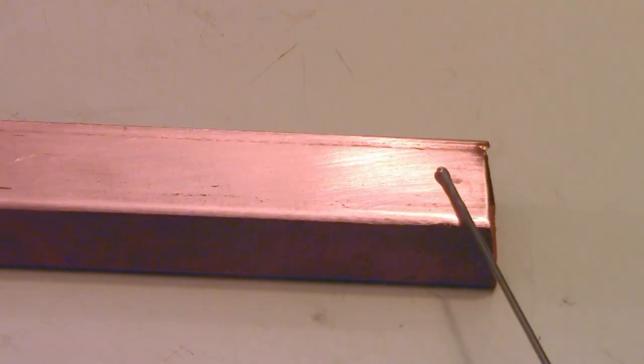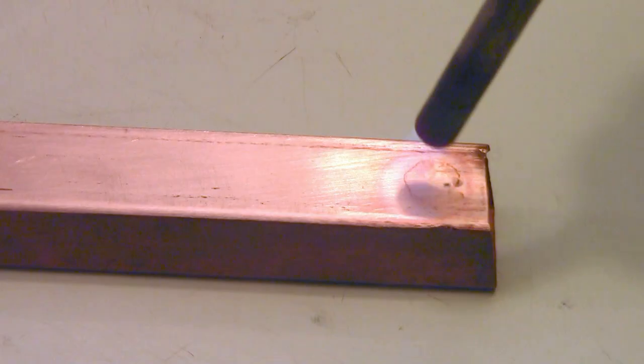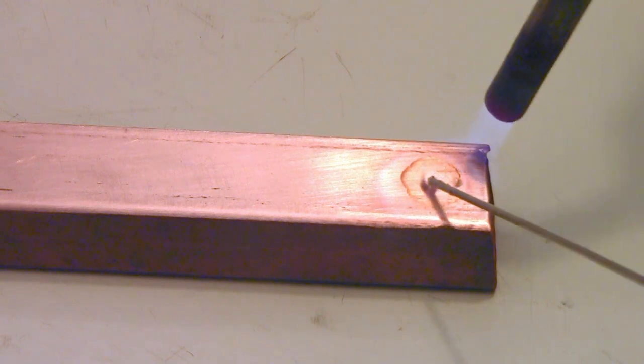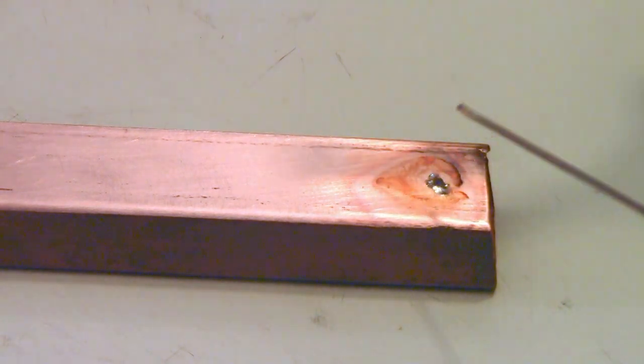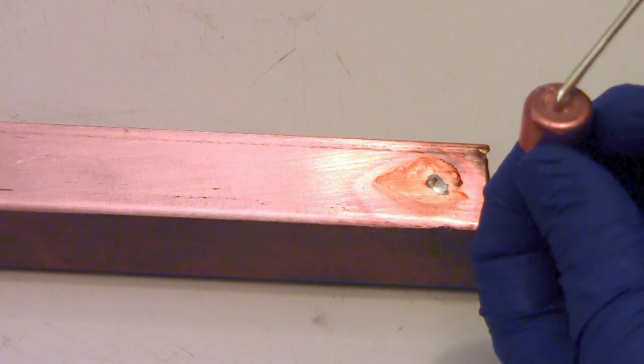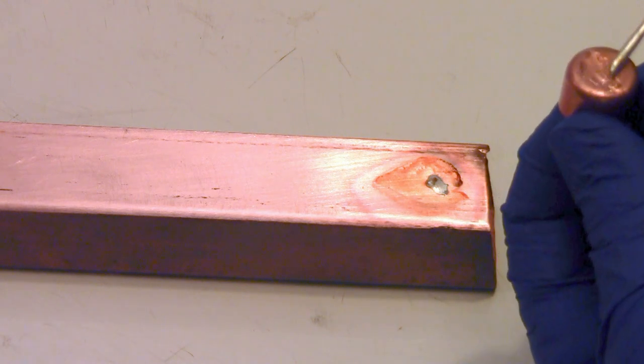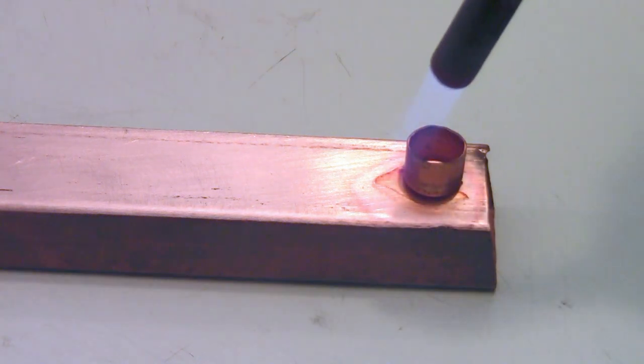Sometimes you want to hide the appearance of the solder. Here's an easy technique. Add the flux to one part, heat like always and add a small amount of Silvaloy 1 rod. Then add a drop or two to the other part. Place on top and heat until you see the flux turn brown.